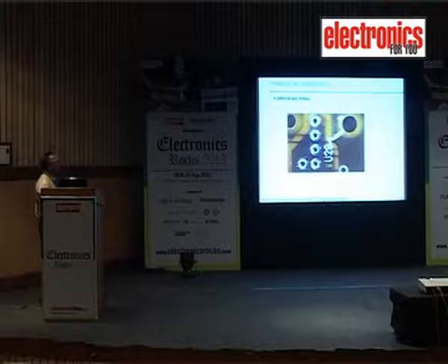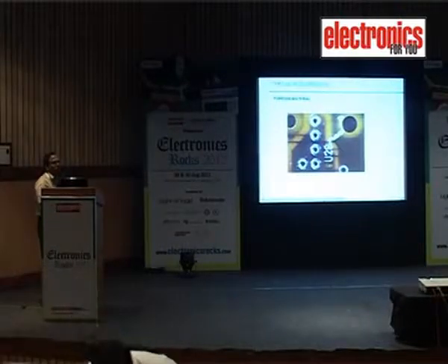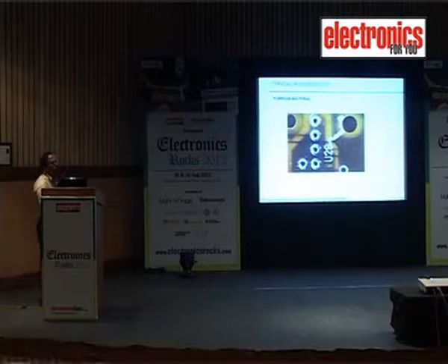And we have seen, sometimes in the laminates which we have procured, some hairs or hair-like structures got entrapped in the lamination process. These contaminations can lead to failure. It is a rejectable criterion. And while making multilayer boards, we have to ensure the cleanliness of each layer, and the whole process is done in a clean room of class 1 lakh.